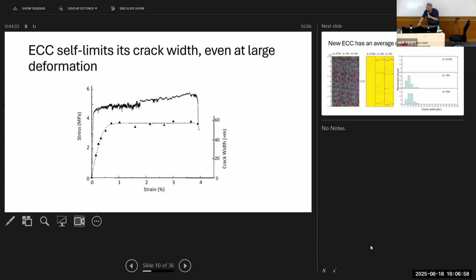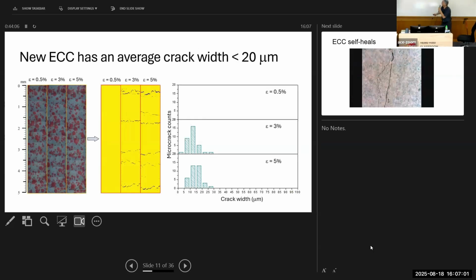Okay, and more recently, we developed versions of ECC, and this is showing different strain levels, 0.5% strain. Later on, increasing the strain to 3% and then up to 5%. You see more and more of these micro cracks develop, and we measure the width of these cracks. Let's move directly to the lower panel here. At 5% strain, very large strain before it finally fails, the micro crack widths are roughly about 15 to 20 micron. That's really tiny. You have to use instruments to look for them, right? They are very, very tight crack widths, and that's the reason why these special techniques are used to detect the width of the cracks, because they are hard to measure.